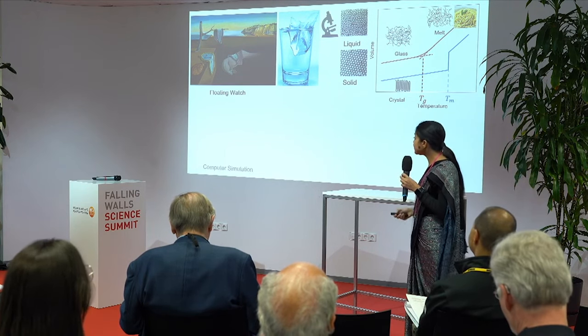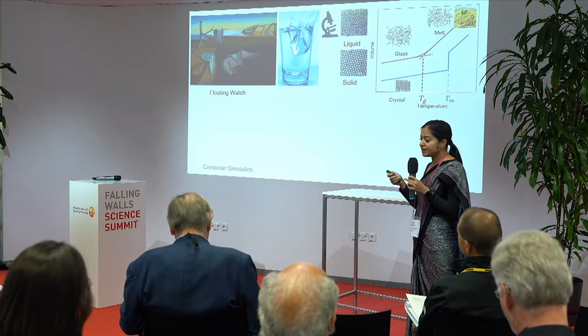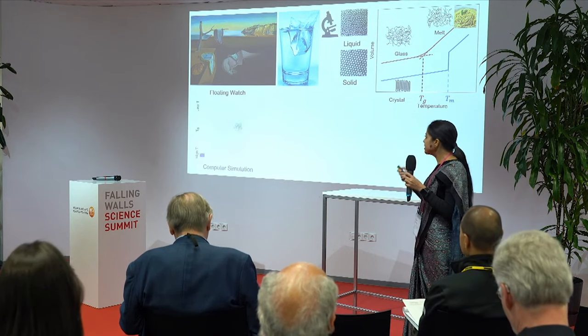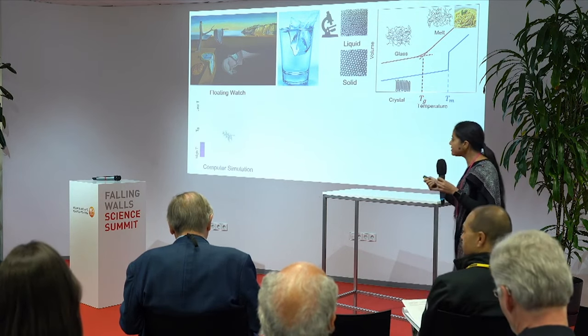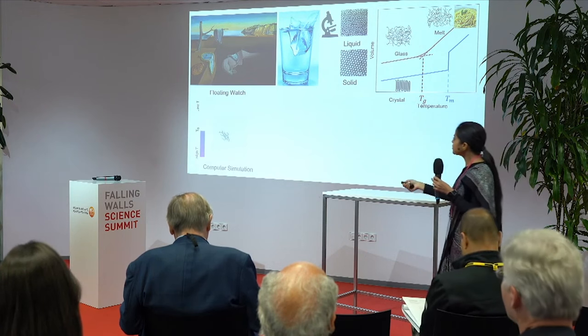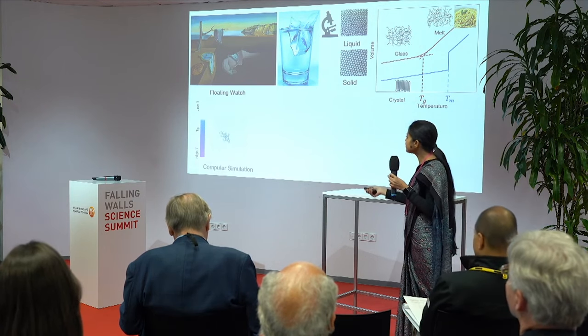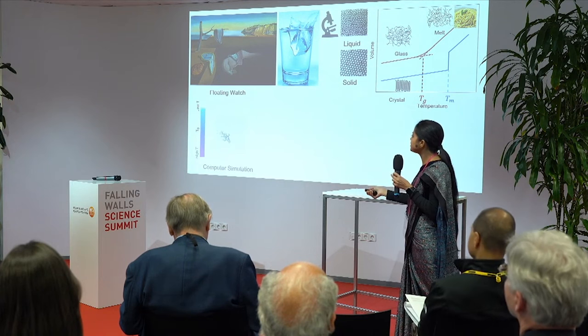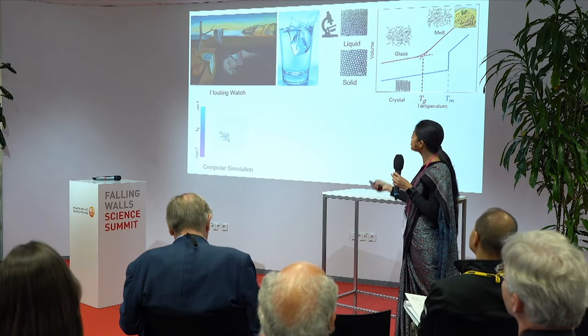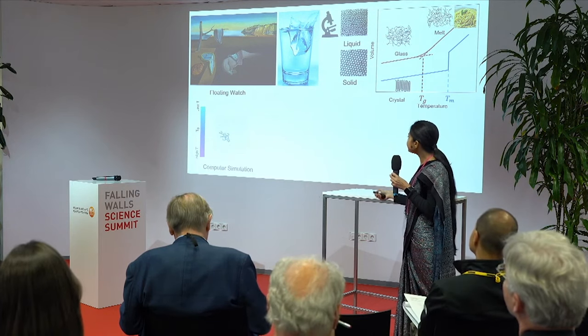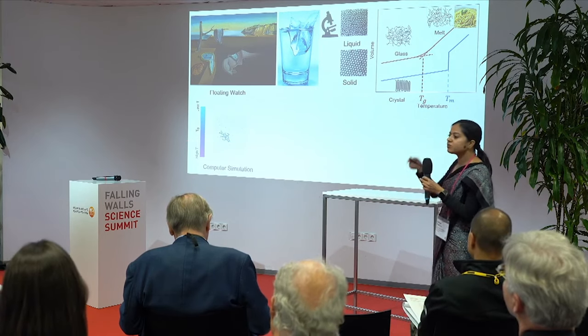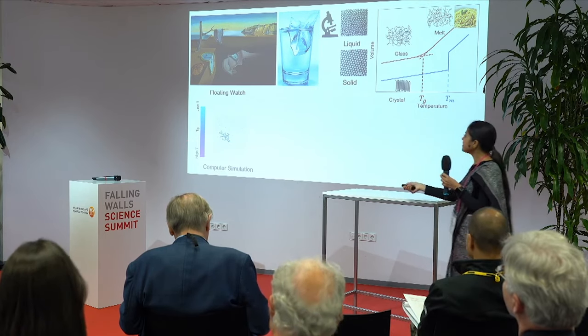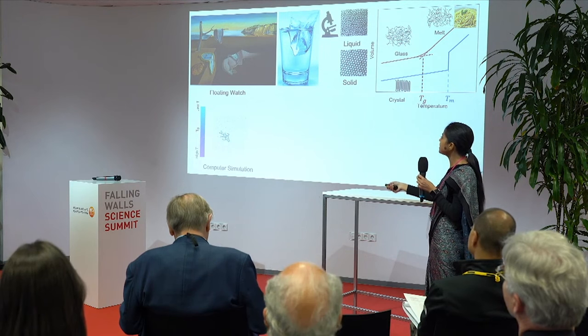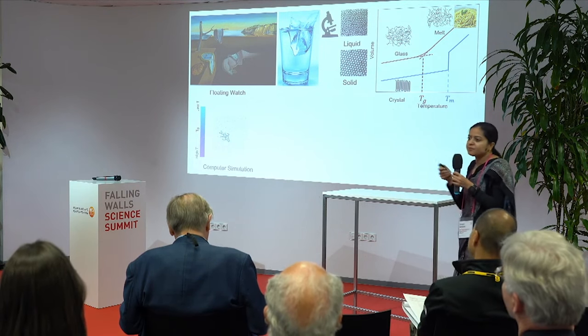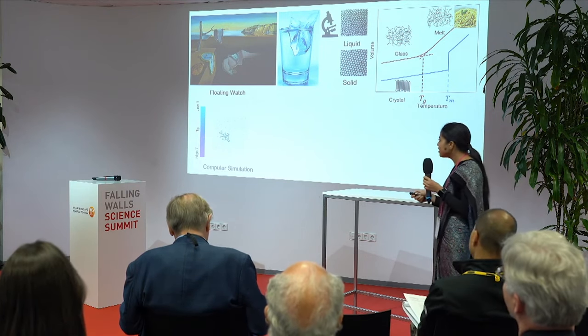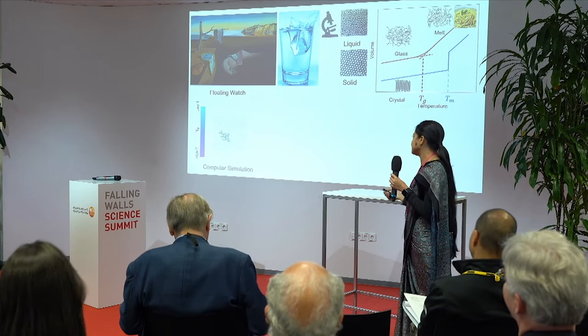And I do computer simulation. I model this synthetic polymer using some potential with some model, and here I'm showing a bulk polymer melt simulation, highlighting one of the chains going from high temperature to low temperature. As you can see, the chain was fluctuating quite a bit at high temperature, and then eventually it goes through the transition and it's frozen. It's just vibrating around something. And we want to identify the transition.